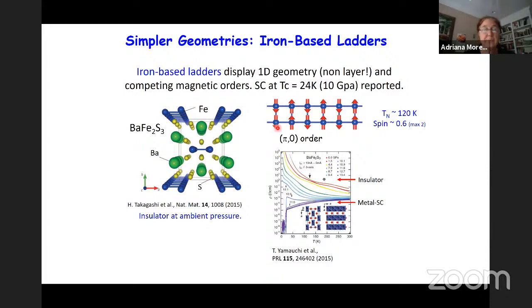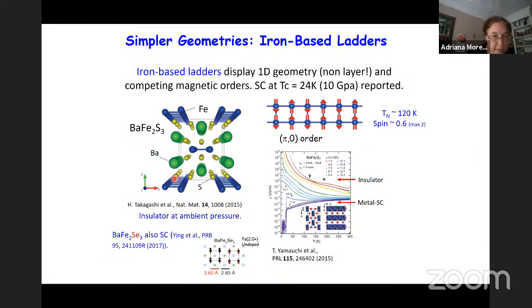There are more materials with ladder structures. For example, this has the same structure, but replacing sulfur by selenium, we have barium iron selenium that also becomes superconductor under pressure. And at ambient pressure, it has this block-like magnetic structure, which is, so these are ferromagnetic blocks coupled antiferromagnetically to each other.